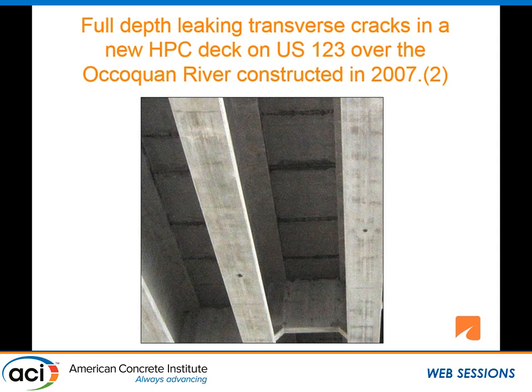And you can see the transverse cracks, spaced 3, 4, 5, 6 feet apart. It varies depending upon the design of the deck. But this is very typical of the underside of decks in Virginia and in many other states constructed over the last 20 years. And you can see they're leaking. They're full depth transverse cracks caused by shrinkage of the concrete because of too much cement.